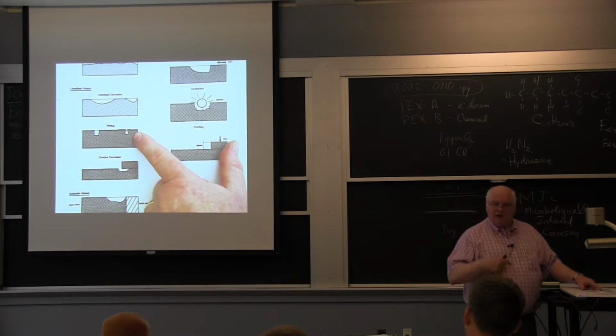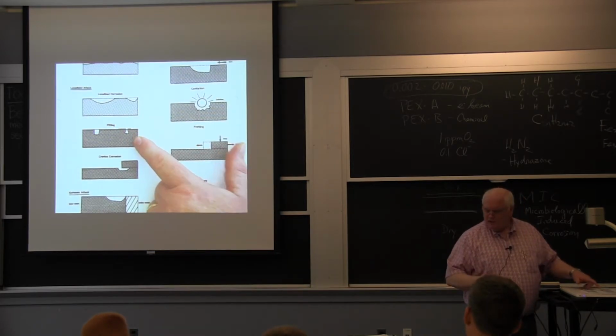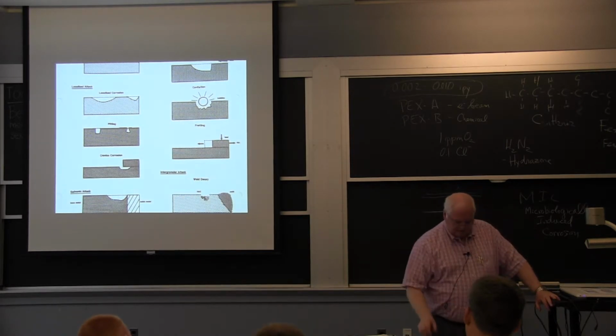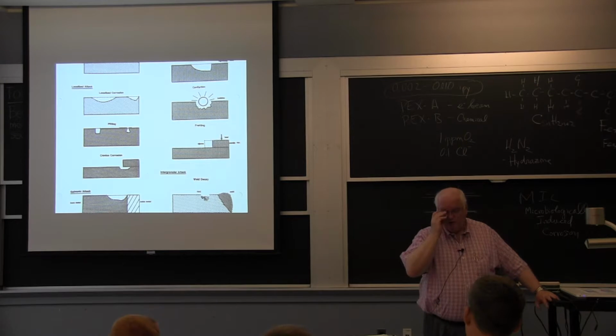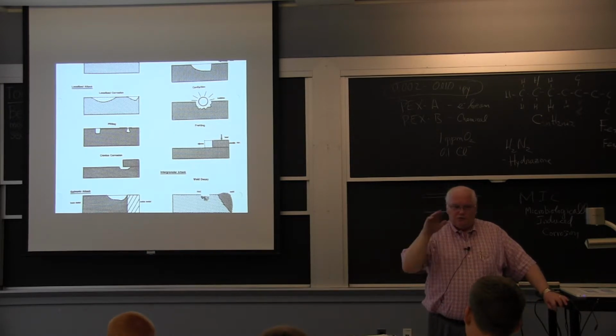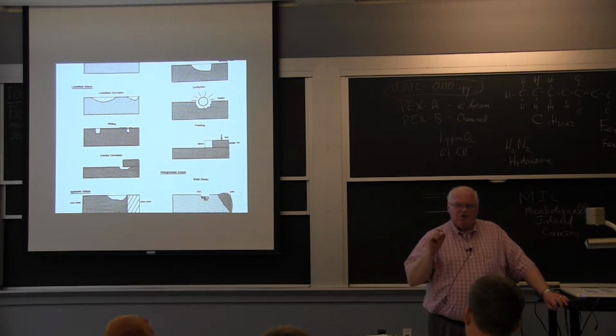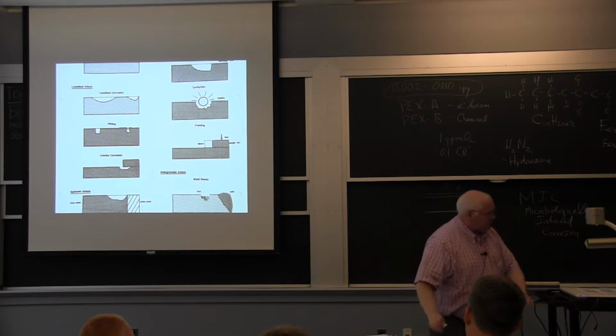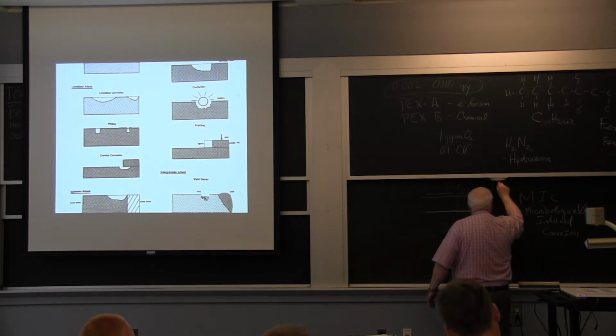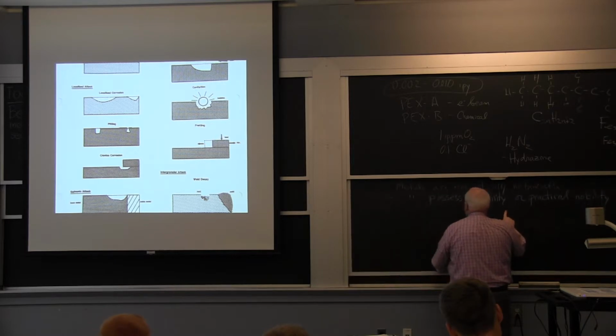And I've seen pits. I talked about the pits in my mother-in-law and the dinnerware. I also had a situation, actually my thesis advisor had a situation over 40 years ago. When copper prices went up in the early 1970s, the stainless steel industry thought they had a great solution to use stainless steel for piping in a home. Problem is you can't easily solder to stainless steel unless you use a very aggressive flux. And so they decided we would plate the outside of the stainless steel with copper. And that way they could solder to the copper.